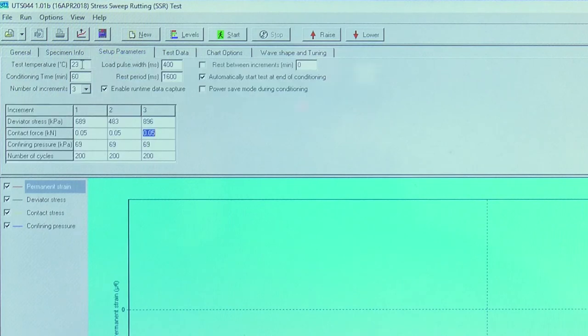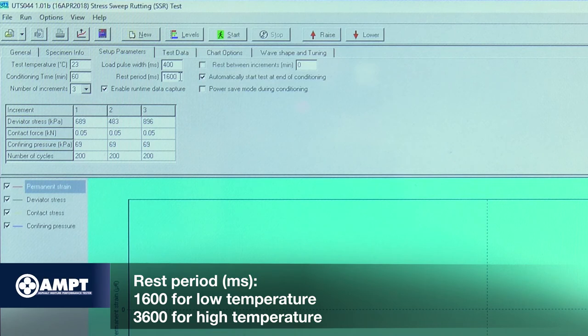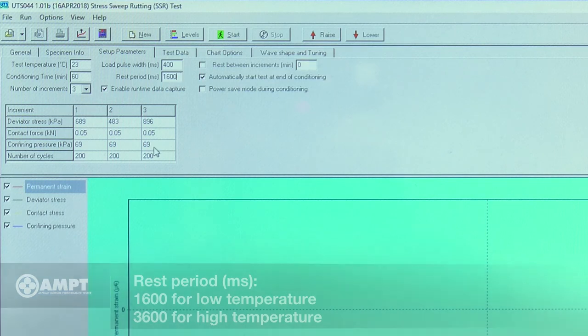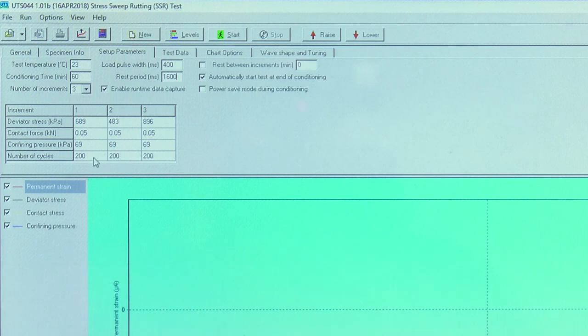Under Setup Parameters, enter the appropriate test temperatures for the testing location, conditioning time, 60 minutes, and number of increments, 3. The load pulse width should be 400 milliseconds. The rest period should be 1600 milliseconds for low temperature and 3600 milliseconds for high temperature. For the increment table, which covers deviator stress, contact force, confining pressure, and number of cycles, refer to the recommended values in the AASHTO TP134 standard. Click Start and save the data file.